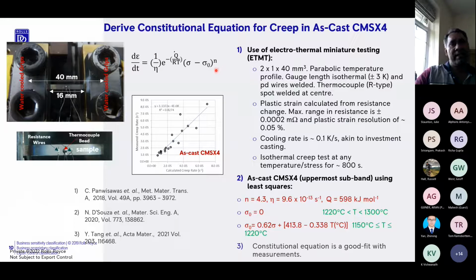The main aim in all of these was to produce an expression of this nature. The reason for having such an expression is that it is quite easily handled by Abaqus or by ProCAST. All that you need in a ProCAST or an Abaqus model are values of the damping parameter, the pseudo activation energy, the backstress term, and the value of n. Now, it would be very useful if in our constitutive equation, we can get eta, Q, sigma naught, and n relatively constant or independent of temperature. Fortuitously, that happens to be the case. The values of n, Q, and eta are independent of temperature. The value of sigma naught, of course, will depend on temperature.